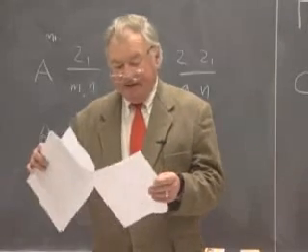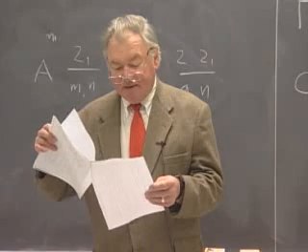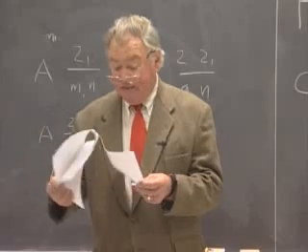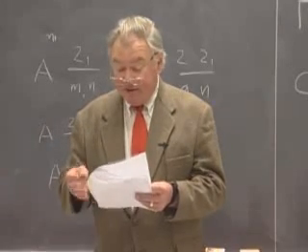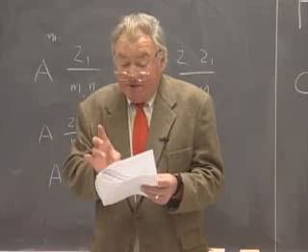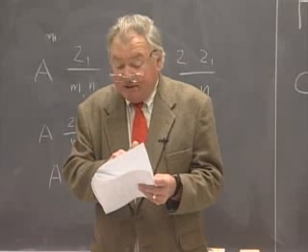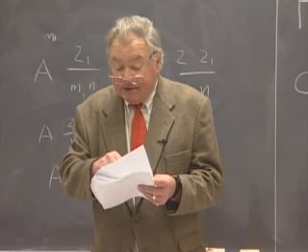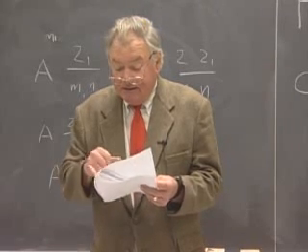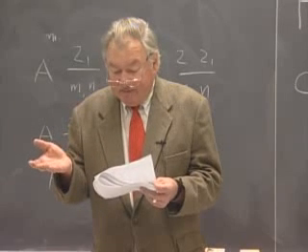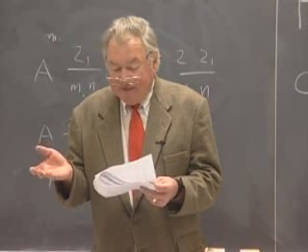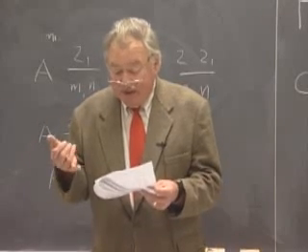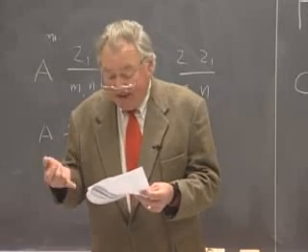Continuing still on, and I think you have the idea now. Same for trigonal crystals. They chose to list those separate from hexagonal. And then hexagonal symmetries. The number is fairly large here because when you take an axis and add it to a primitive hexagonal lattice, for number 168, for example, you get P6, and you can change the 6-fold axis to a screw axis. There are 5 different types of 6-fold screw axes. So there's a P6 sub 1, a P6 sub 2, a P6 sub 3, a P6 sub 4, and a P6 sub 5.